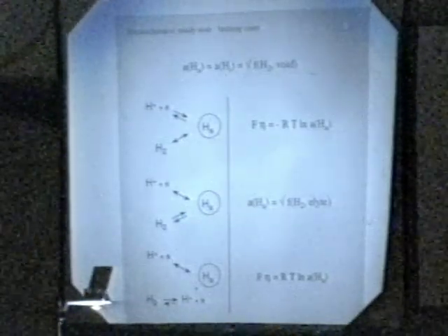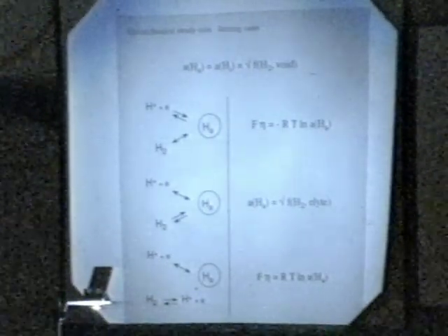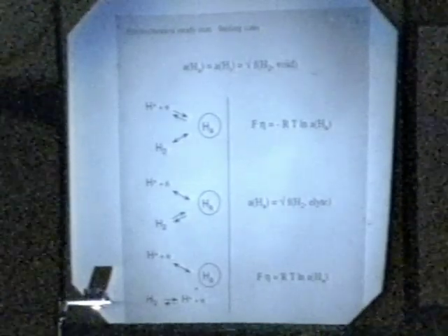In this case, it's a simple matter to show that the chemical potential of adsorbed hydrogen, and hence the loading in a metallurgically unimpaired sample, is related in a manner such as this to the overvoltage. In other words, if we measure the overvoltage versus the reference electrode, we can infer the chemical potential on the surface and hence the loading. This is a highly desirable situation because it's the only situation that leads to high loading. Why is that? Let's consider the second case.